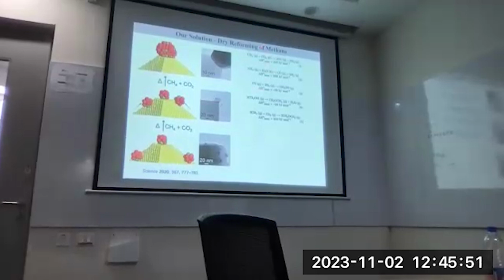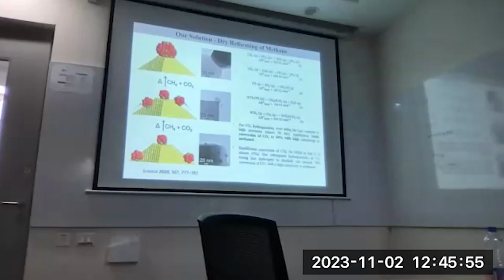And so this is a more efficient way of converting your CO2, and the conversion at equilibrium is almost 98% conversion of the CO2 and 98% conversion of the methane also. At 800 degrees Celsius, that's the equilibrium. Almost completely converts. And then we can use this to form alcohols, hydrocarbons, anything. Fischer-Tropsch is a very common process. All plastics, many of the polymers, everything is done through CO and hydrogen as the starting material.